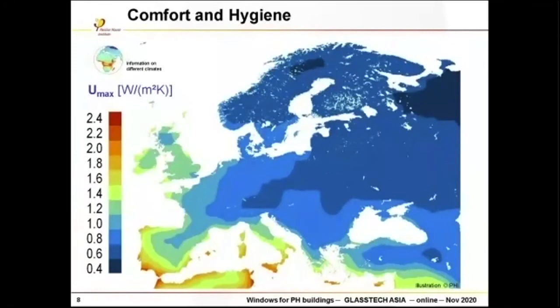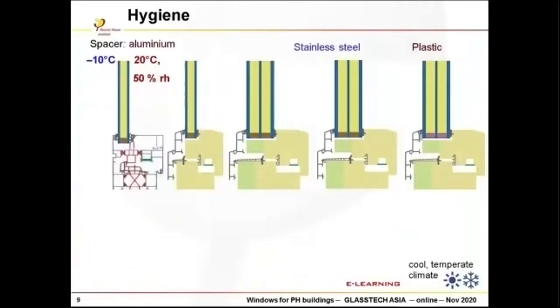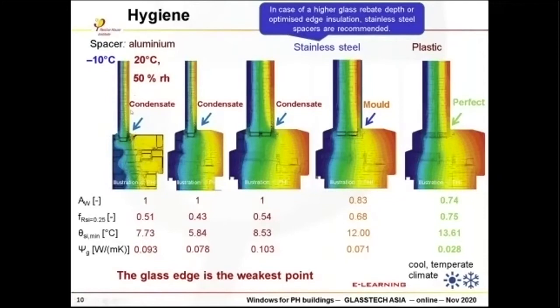From these thoughts, you can straightforwardly set up this map, and this is for the example of Central Europe and Eastern Europe. You see, the more you go to the colder areas, the lower the U value you need. The next point is the gap between glass and frame, the connection between glass and frame and the edge of the glass. Normally a spacer is installed, and if the spacer is not good enough and the glazing rebate is not deep enough, you will have a thermal bridge there, and this you can see here. If you do it not well enough, you will have condensate or even mold growth, and only if you go for a very good glazing edge, you will get these low values and very good performance with respect to hygiene and comfort.